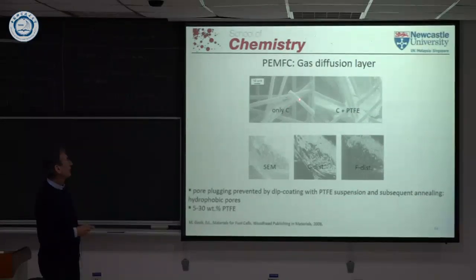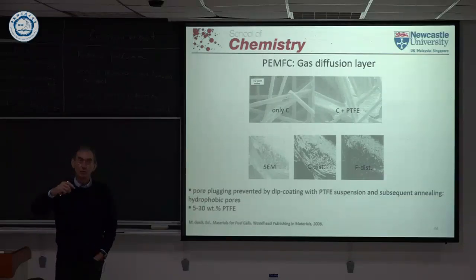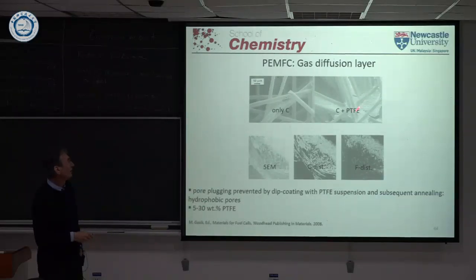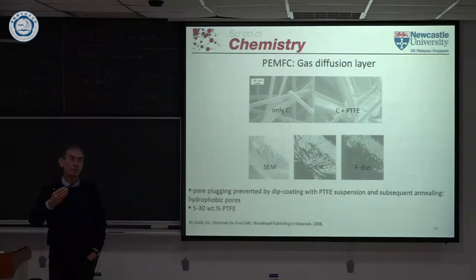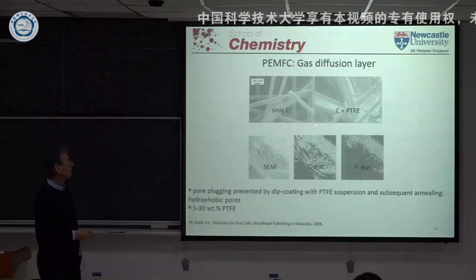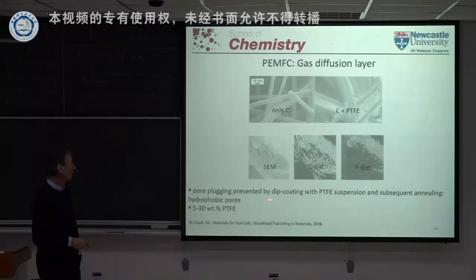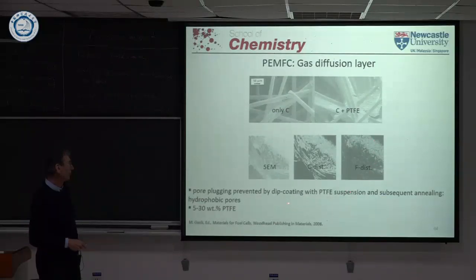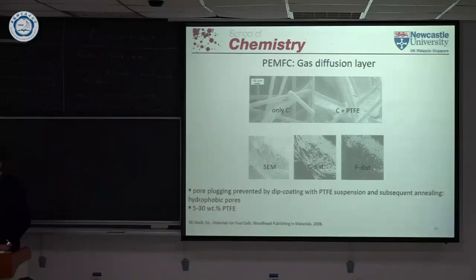This shows you some materials in micrographs. Here you have only carbon material. Then you have some PTFE. We talked about PTFE. So essentially PTFE itself is water repellent. And you put this in to get the water that's being produced by the reaction out of the fuel cell, so that the pores are not blocked by water molecules. And this shows the chemical distribution of carbon, and here fluorine, that's from the PTFE, you can see the fluorine. So there are a number of pre-treatments of these media that are very important to do so that you get a full functioning of the fuel cell.